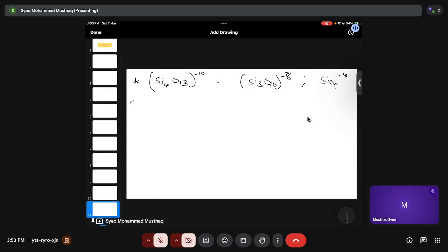So at first you will have silica, right? Now you add oxygen, and some silicon atoms will break away. So some silicon atoms will come out; they will not be in a chain or 3-dimensional structure anymore. Now I am trying to add more calcium oxide, which means oxygen is being added, so the structure keeps breaking.